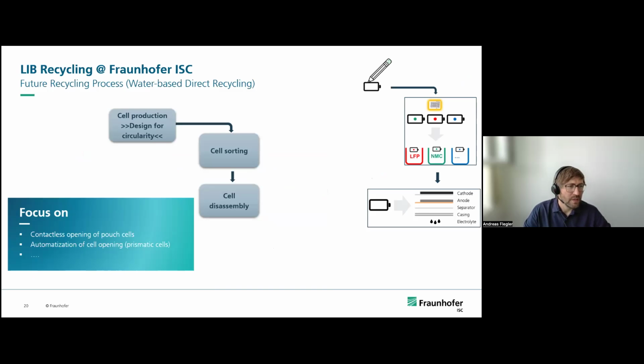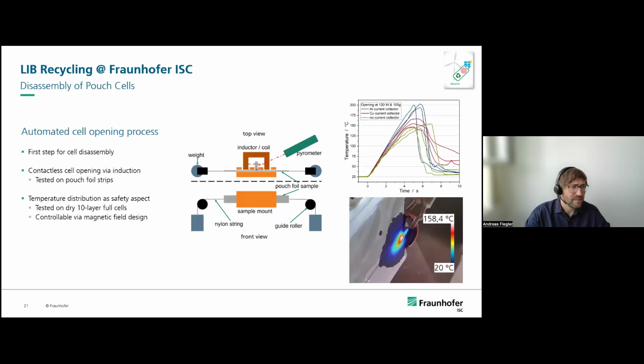In the next step, we look at the cell disassembly. In the cell disassembly, we look on the one hand at the opening of pouch cells, so the contactless opening. Here we use an inductive method. We focus the inductive field on the sealing and open it via melting the polymers. And here we have to make sure that we have a spot and don't burn the electrolyte, the flammable electrolyte. With this approach, you can open pouch cells contactlessly and separate cathode, anodes and separator from each other.